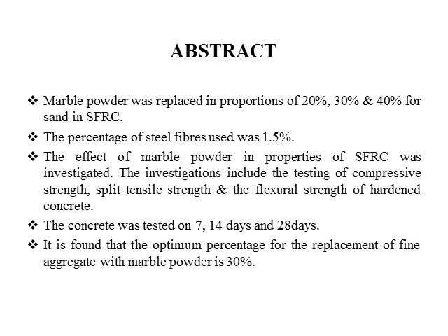The percentage of steel fibers used was 1.5%. The effect of marble powder on the properties of SFRC was investigated. The investigations include the testing of compressive strength, tensile strength and flexural strength of hardened concrete. The concrete was tested at 7, 14 and 28 days. It is found that the optimum percentage for the replacement of fine aggregate with marble powder is 30%.